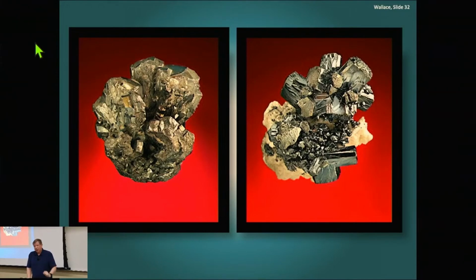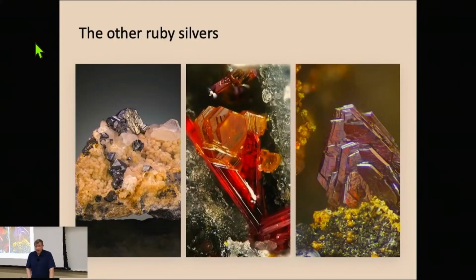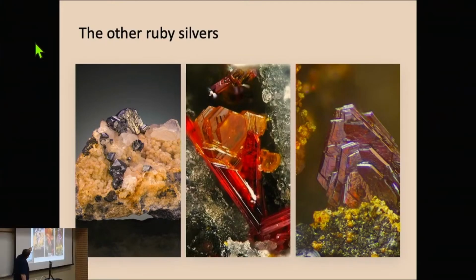But just like acanthite, silver sulfide, a phase change is going to occur for these two. So we actually have other ruby silvers, which are low temperature forms of some of these minerals. In the middle there is xanthoconite. It's the Moroccan piece, and you can see these little hexagonal plates. That is the low temperature form of proustite. So you heat that up to around 190 degrees, maybe C, and it's going to turn to a structure that's going to give you the proustite.